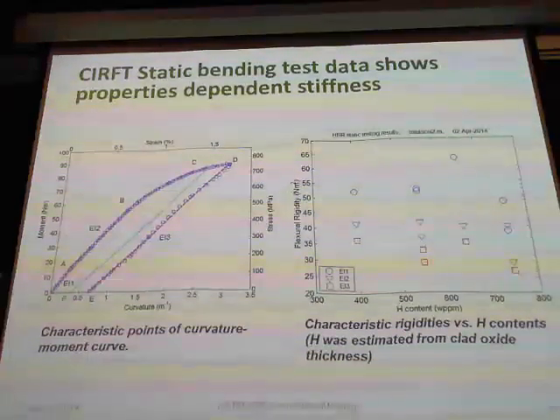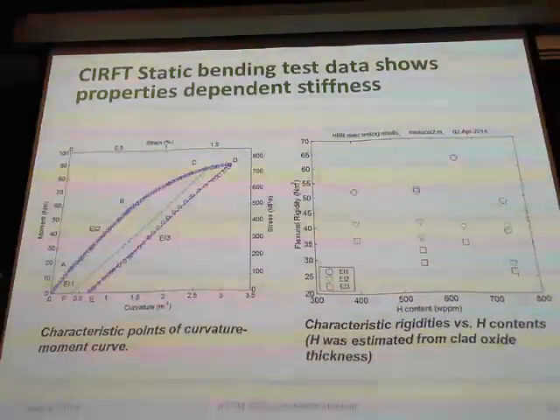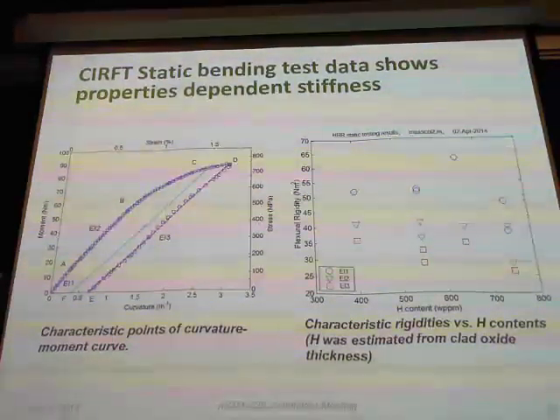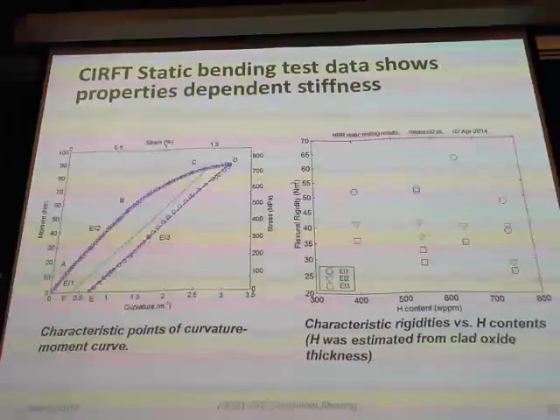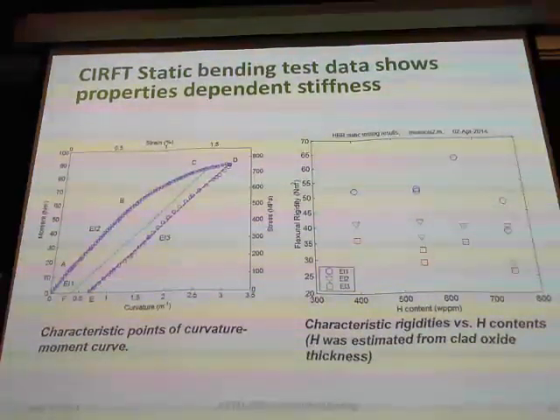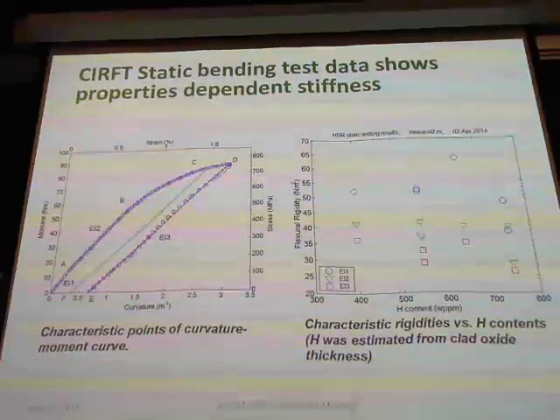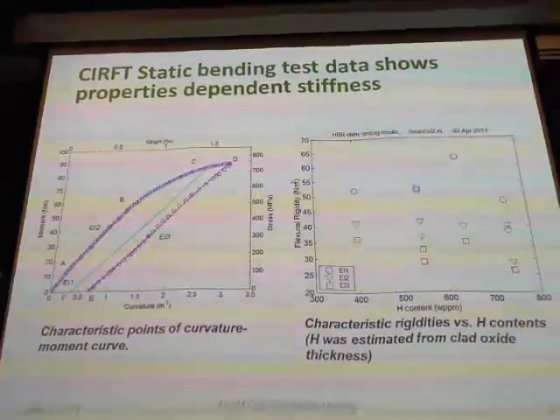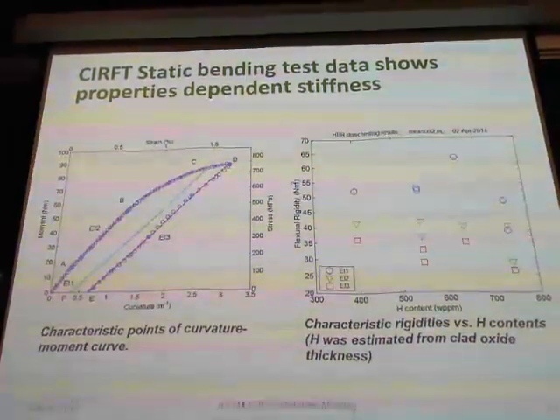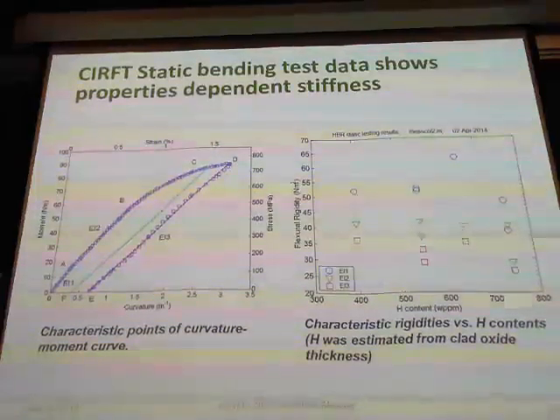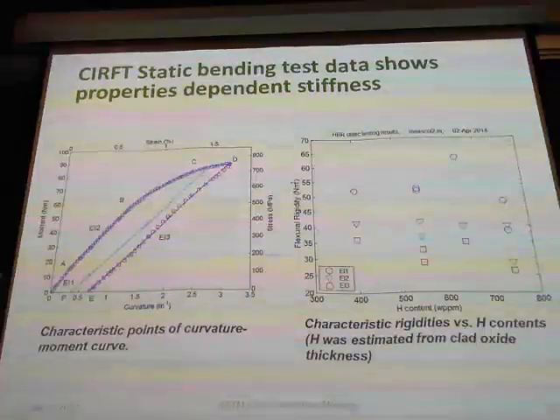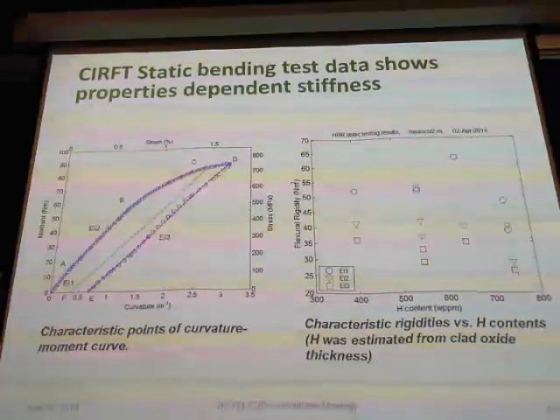Yeah. So we do find a flexural rigidity, equal to moment divided by curvature, depending on hydride content, hydrogen content. And it's very counterintuitive, because normally you'd think that with hydride the material becomes more brittle, so flexural rigidity should go up. But actually it's the opposite, it's going down. A lot of what we're doing here, people keep questioning, how come? But people need to bear in mind this is a composite structure material, not a single isotropic one, so common sense doesn't apply.